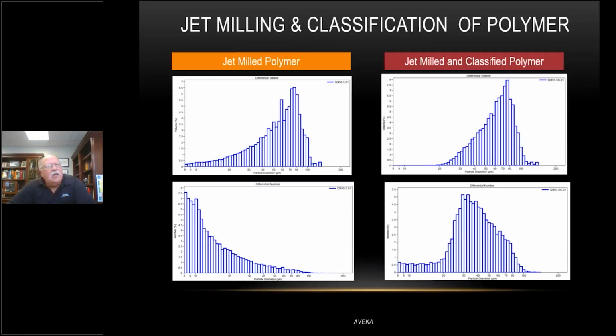Well, let's consider grinding of a polymer. This is an engineered plastic that's used for additive manufacturing. In this particular case, we jet milled the polymer, and I'm giving you 2 particle size distributions here. One is a standard volume distribution. You can see most of the product is in the size range that we want, that 50 to 100 microns. But when we classified it, we still had to get rid of these fines because the fines changed the flow characteristics of the material to an adverse effect. So we classified out the fines, and we did many different test classifications, and we got rid of the fines all the time. But we were getting all these variable results that we couldn't understand until we looked at the number distribution.